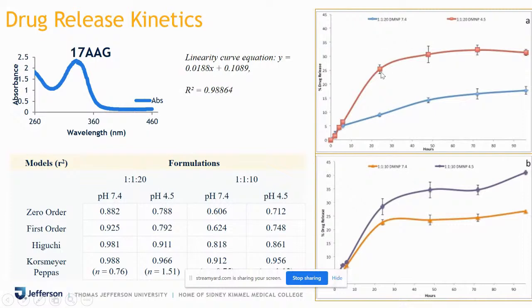The two figures shown on the screen belong to two formulations, that is 1:1:20 and 1:1:10. They were measured under two pH conditions, 7.4 and 4.5. The reason for having an acidic pH is that some studies suggested that the tumor microenvironment is acidic, approximately pH 4.5 to 5. So we took 4.5 as a mark for checking our release kinetics. What we found was that the release from 1:1:10 was slightly higher than that of 1:1:20, which is again an indication that the polymeric shell is driving the release kinetics.